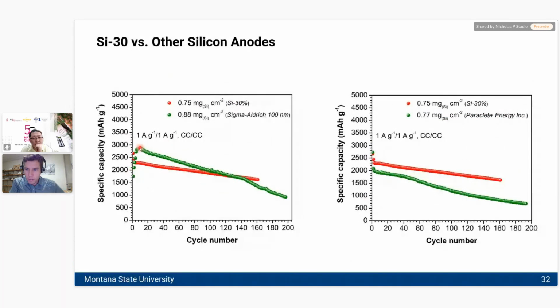On the left, we have the previously best sample we had ever gotten our hands on. This silicon, or sorry, this 100 nanometer nanoparticle from Sigma Aldrich, unmixed. And you can see that while that material did better in early cycles, it always did worse in later cycles. And so we now had a much better material than we ever had as a pure silicon nanoparticle phase. This was the best one we ever made in our own lab.